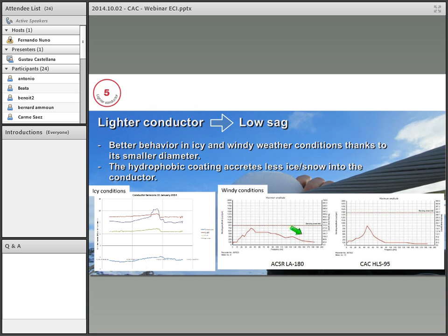If we compare the two graphs, you can realize that this here is the frequency of the wind. On the aluminum conductor, the vibration happens in a wide range of frequencies, while in the copper conductor it was only a small range. It was between 40 and 60 Hz, while in the control conductor it was between 20 and 130. That's an interesting property because it shows that the copper conductor has a self-damping characteristic.